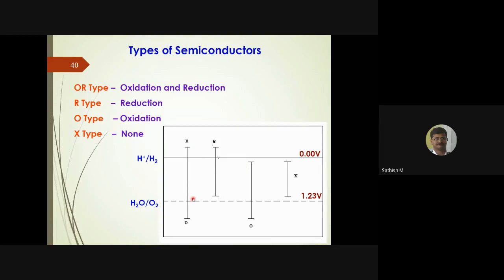Based on the hydrogen evolution reaction, that means the water splitting reaction, this is 0 volt for hydrogen evolution. For oxygen evolution, you need 1.23. So if I have a catalyst like this, where the valence band is here and the conduction band is here, then I can do both the oxidation reaction and the reduction reaction. So this catalyst is more appropriate. If I have a semiconductor where the valence band is here and the conduction band is here, then I can do only a reduction reaction. I cannot do oxidation of water. So if I use this particular catalyst, I cannot make complete decomposition of water. I can produce hydrogen, no doubt, but instead of oxygen evolution, I need to do some other reaction. Still, I can do hydrogen evolution.